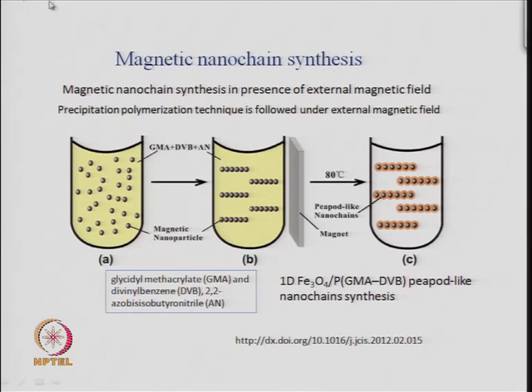That is of importance. So, what people have done, they have taken some magnetic nanoparticles. So, these black spheres are magnetic nanoparticles, and can be iron oxide, and then it is put into a solution of some chemicals which can be polymerized. So, you add glycidyl methacrylate and divinyl benzene, DVB. So, GMA and DVB are these, and then you also add 2,2 azo bis isobutyronitrile, which is normally called AIBN, A for azo and I for iso and butyronitrile. So, BN. So, these three reagents can be added.